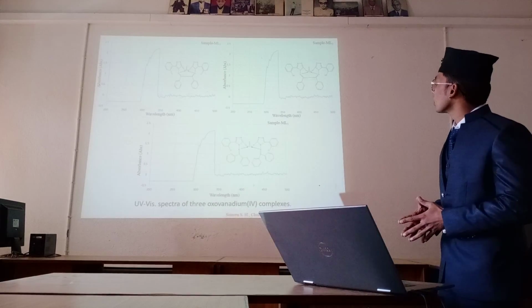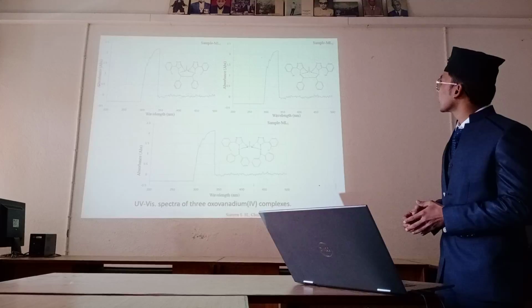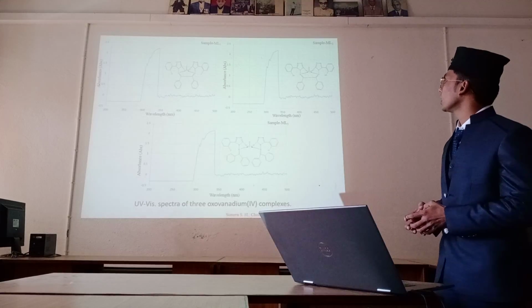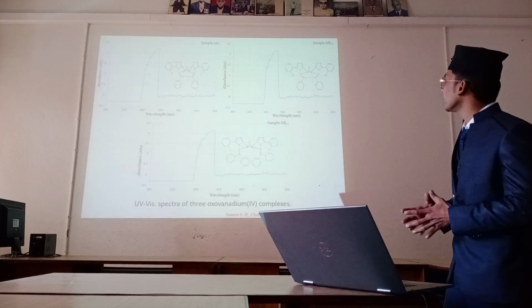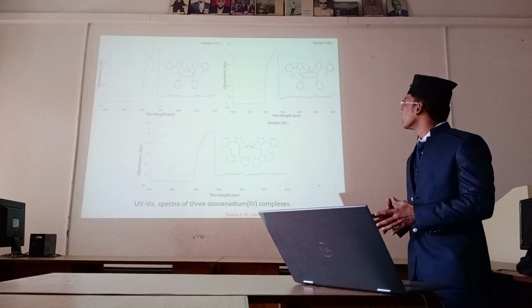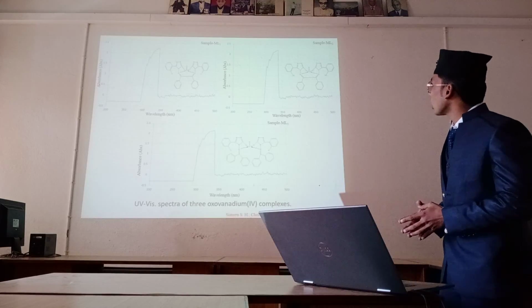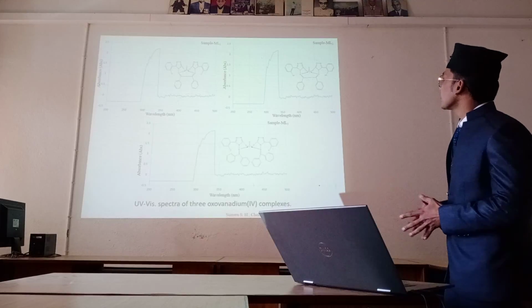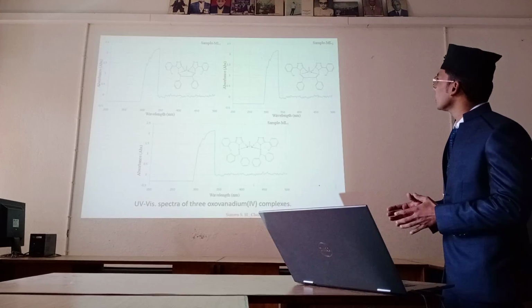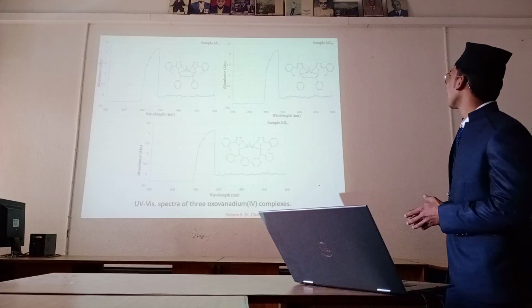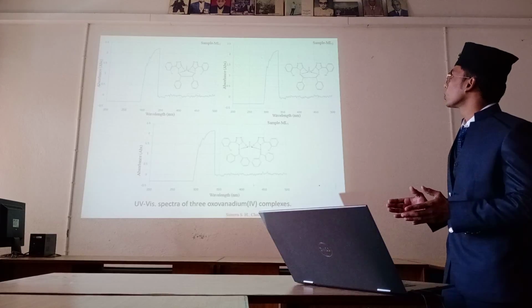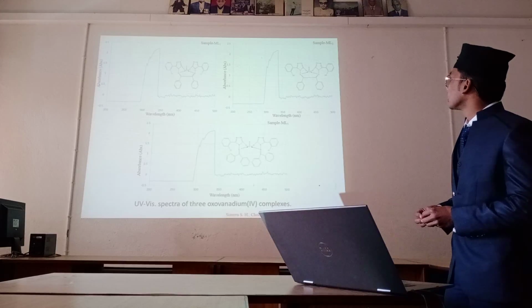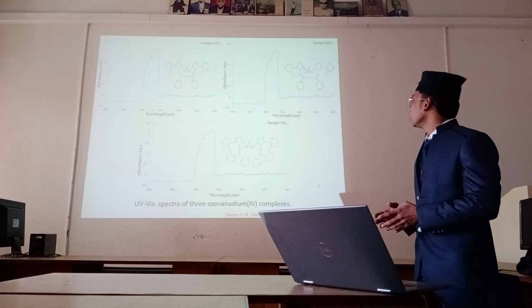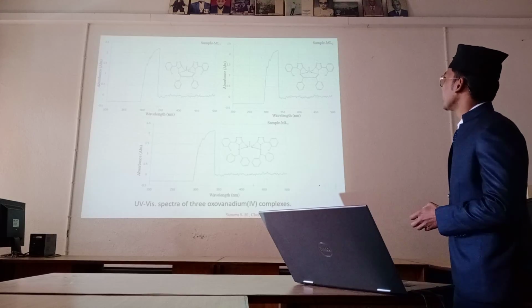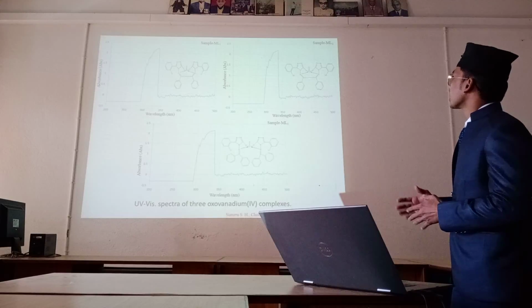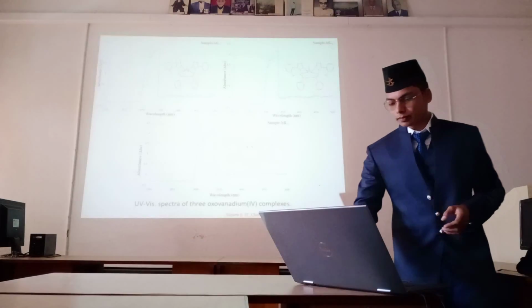From the analysis of this UV-visible spectra, we can see that the spectral band present near 310 to 315 is due to the pi to pi star transition of the azomethine group. Another spectral band present near the 320 to 325 range is due to the intraligand n to pi star transition. And the intense peak near 340 to 350 is due to the ligand to metal charge transfer and d-d transition.